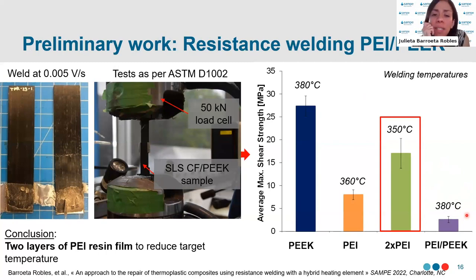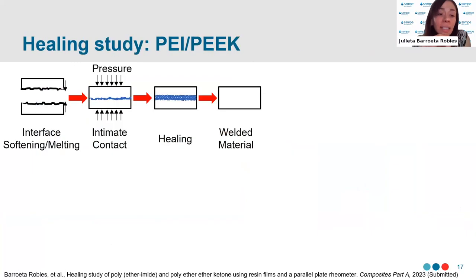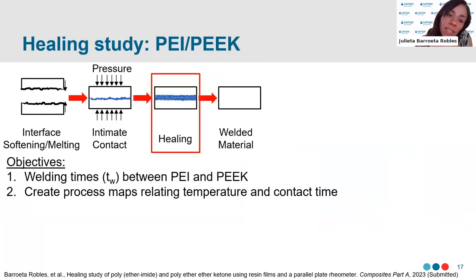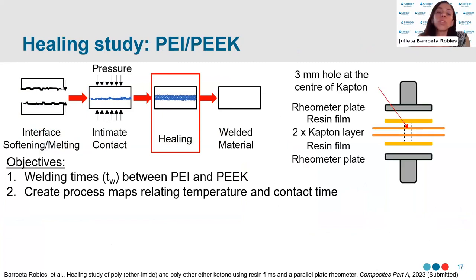From this work, two things became evident. One, that we needed a better understanding of what's happening between the resin film, PEI, and PEEK, and also that this was quite a bit of trial and error. This led then to conducting a healing study of these two dissimilar polymers with the objective of obtaining the welding time. Meaning, how long do we need to attain a full weld, or a degree of healing of one? This would allow us then to create process maps, which would allow us to relate the temperature and the contact time. To do so, we used a parallel plate rheometer, as this is a piece of equipment that can be found in most composite processing facilities.